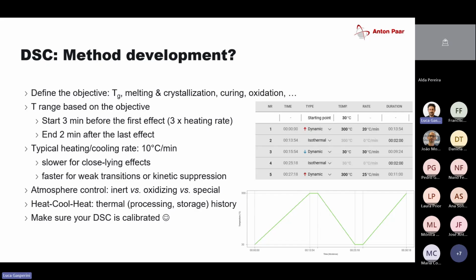Of course, you can heat slower if you have close-lying effects and you would like to separate them. A slower heating rate will help this. Or you can go even faster. If you have weak transitions, like a weak glass transition, the higher the heating rate you use, the stronger the signal becomes. So faster if you have weak transitions, or if you need to suppress kinetic effects. So second-order transitions and chemical reactions, the faster you heat, the reaction will happen at a higher temperature.